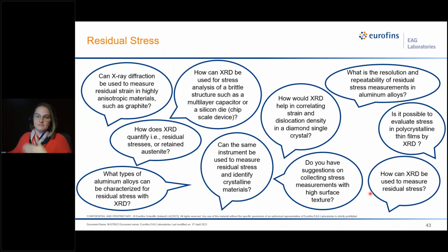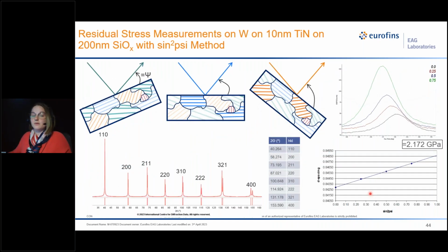Now, another thing that a lot of people wanted to measure was residual stress. The most typical residual stress measurement is the sine squared psi method. What's happening here is we're looking at tilt with respect to the surface, which is technically the chi physical axis, which is the tilt of your sample. The slope of the line is a function of stress, elastic modulus of the material, and the Poisson ratio. In this tilt, the green crystals are diffracting. In this tilt, the blue crystals are diffracting. And in this tilt, the orange crystals are diffracting.